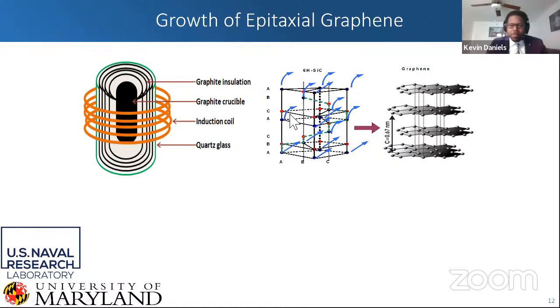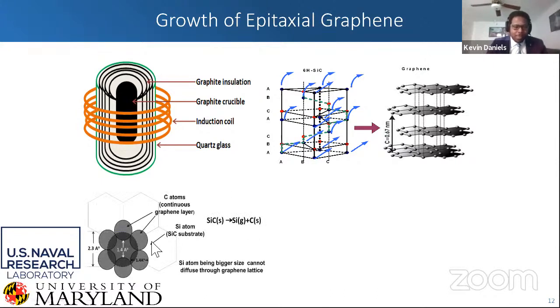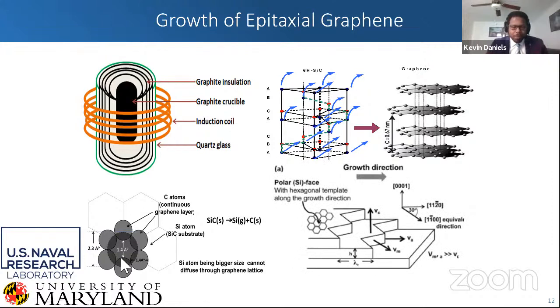And the carbon and silicon in silicon carbide have different vapor pressures. So the silicon will sublimate out of the material, and the carbon will remain behind and restructure itself to form these really nice layers of graphene. Now, this process is also self-limiting because, as you can see, the silicon atoms here are much bigger than the carbon atoms of graphene would allow. So it's self-limiting because the silicon can't get through this graphene lattice. The actual growth, especially on the silicon face, is this step flow mediated growth, where you get a lot of growth from the A and M planes of the silicon carbide that propagate along this C plane to form these very nice layers of graphene.